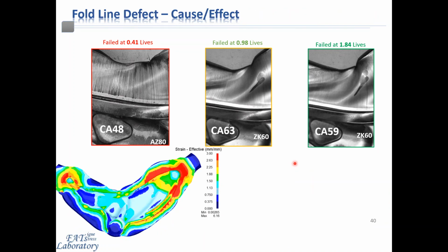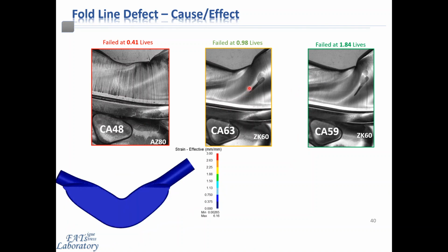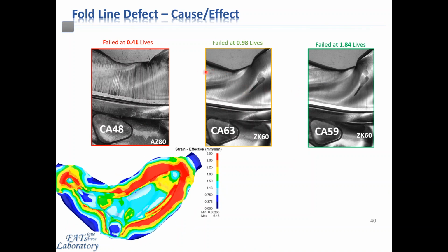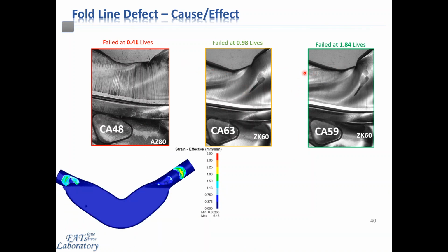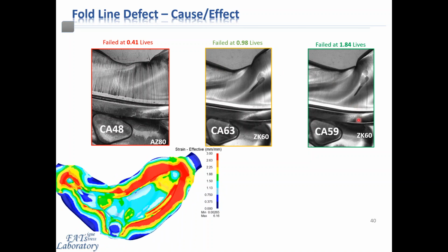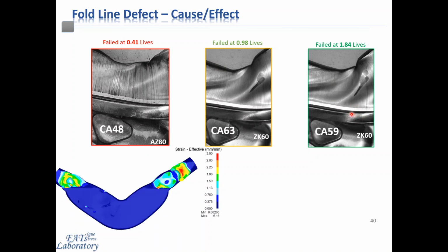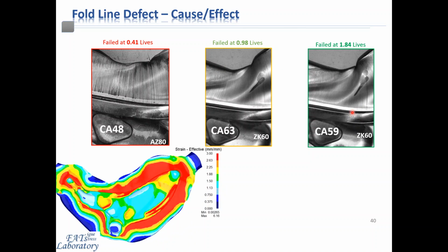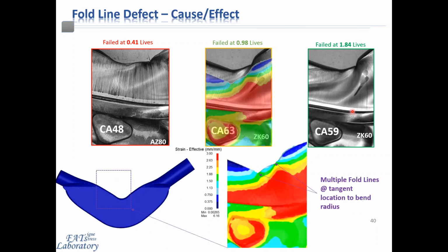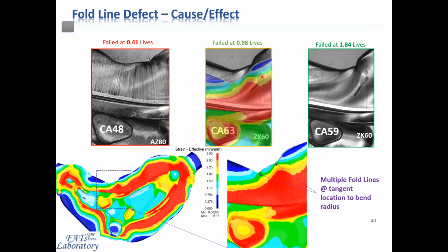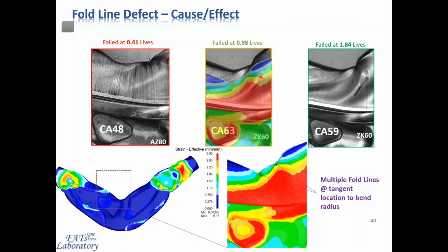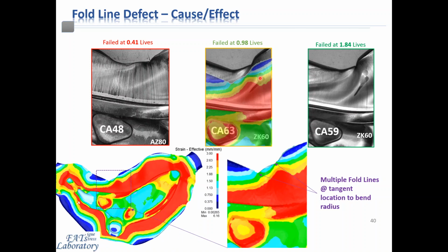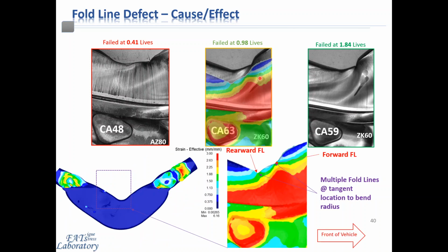Now, if we look at the excess material surrounding the forging prior to machining, we can see evidence of two fold edges at the outer perimeter of the material, which originated in this critical region of the arm. Coupling these observations with the forging simulation result, we can also see two fold line edges manifesting themselves in these regions at the tangent points, or the points tangent to the bending radius of the first forging operation.